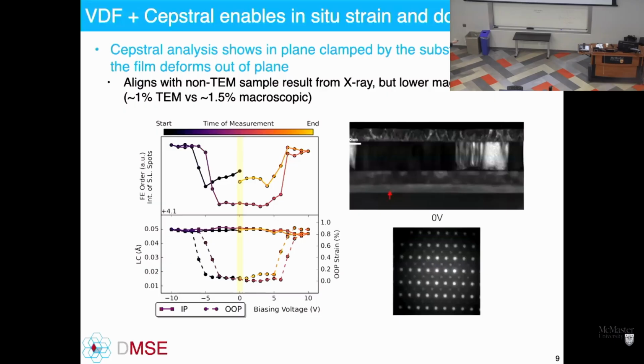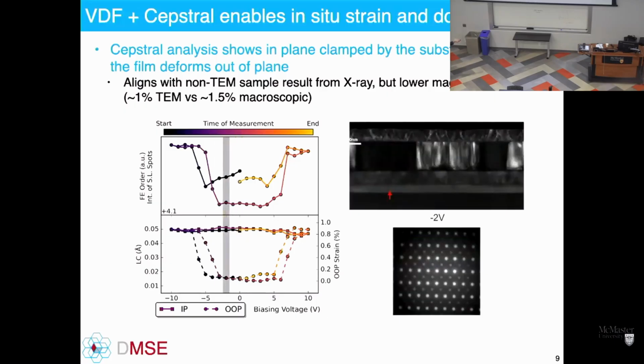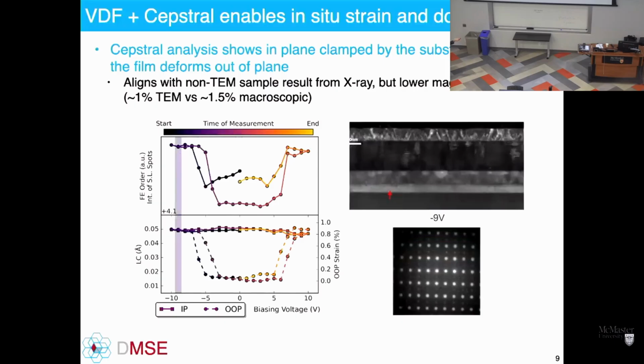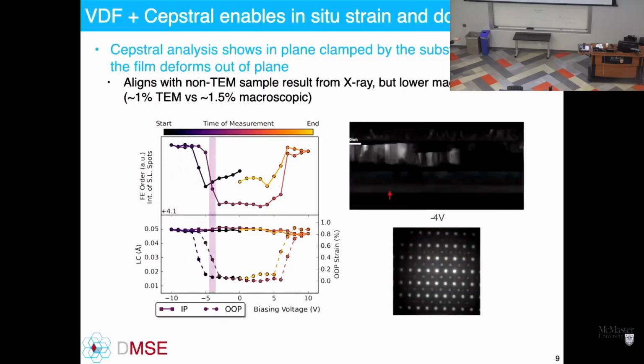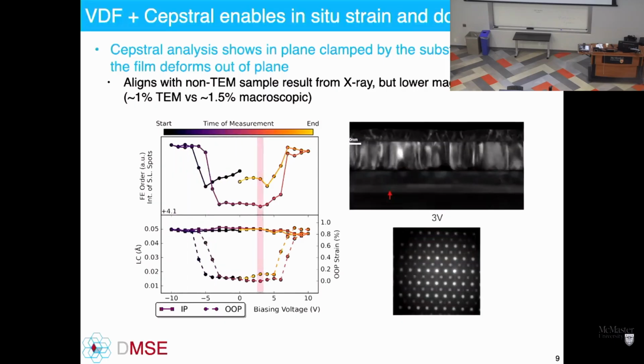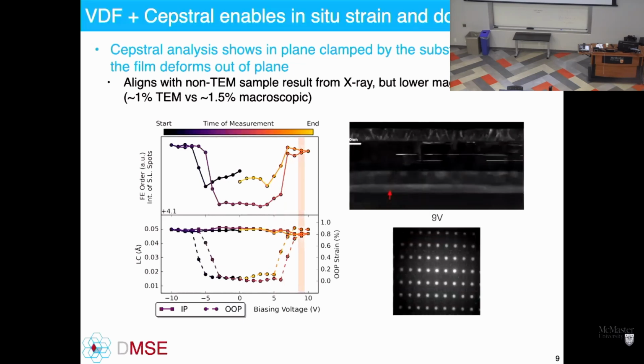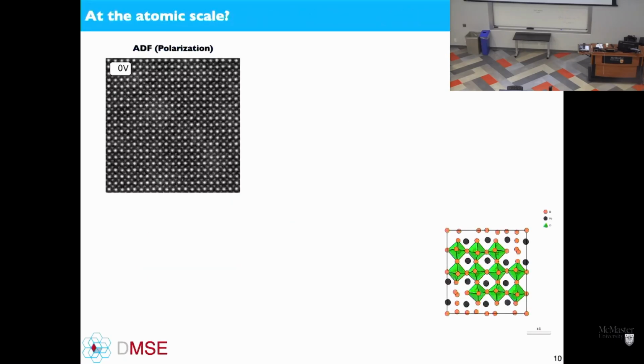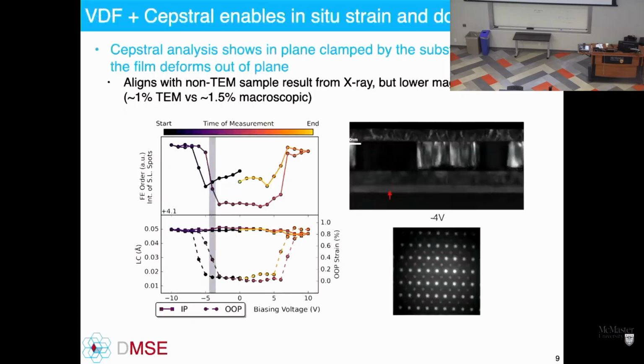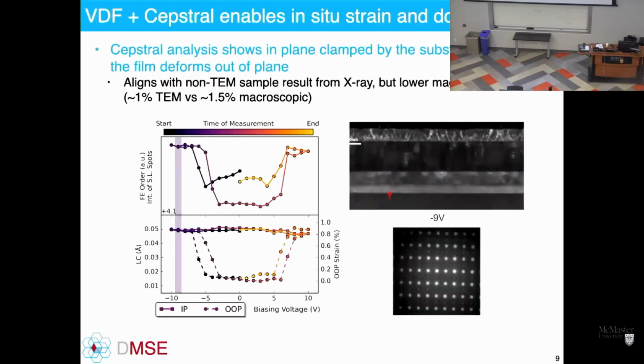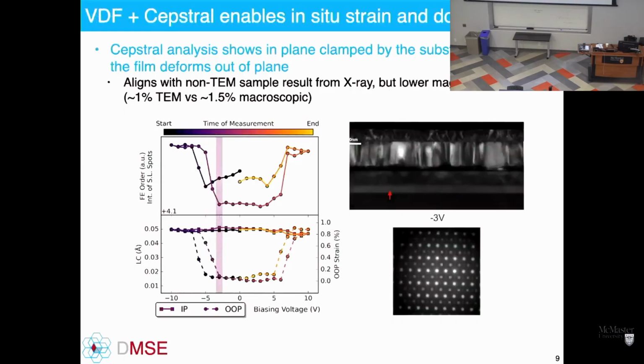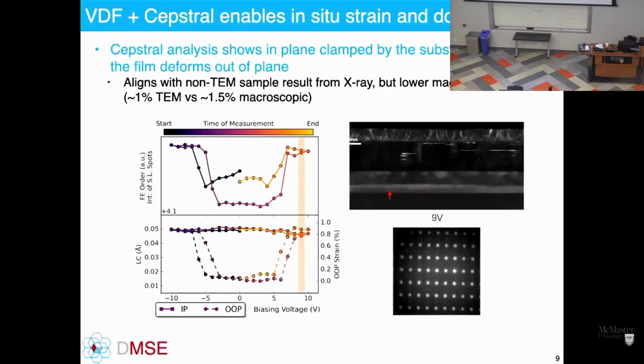And if you look at the diffraction pattern also from this case, you'll see that those satellite reflections completely disappear, and the other spots come in to indicate that antiferroelectric to ferroelectric order, and you can see how that's changing across the film. A couple of things to note is the whole film doesn't transform. Even at full bias, the film isn't fully transformed, and you also see that flickering. That's going to become important in a moment here.